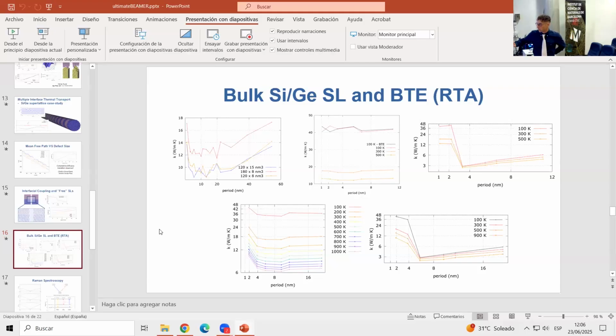Well, I'm not sure if I'm answering correctly, but in order to introduce the boundary resistance between different layers, the BTE actually uses the acoustic mismatch model. It is implemented as a sort of trick: you take a result from something which doesn't have much to do with the BTE, and you plug it into your BTE to compute your simulation. This is one part of the answer. The other part is that we put just periodic boundary conditions on the plane perpendicular to the transport direction, and of course no periodic boundary condition along the transport direction. So basically the acoustic mismatch model is reproducing this minima. Okay.